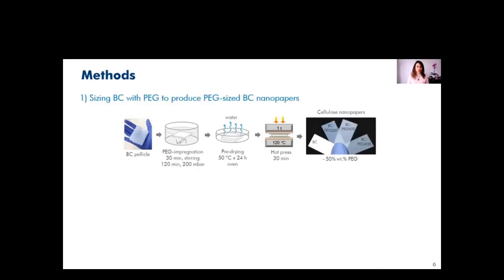So for the methods, we have as a first step the sizing of the BC with the PEG to produce the PEG-sized BC nanopaper. I show here a schematic representation of the process. The wet BC pellicle, never dried, was immersed in the liquid PEG, the three different PEGs, and then after that was pre-dried in an oven with a slow process to remove the most amount of water possible. After that comes the consolidation process in a hot press for 30 minutes. As a result, we have cellulose nanopapers, as you can see in the image in the presentation, which have an average of 50% PEG in weight. These nanopapers are dry and they don't show any wet film.